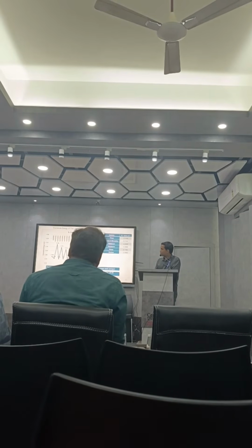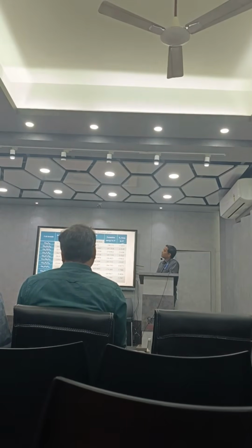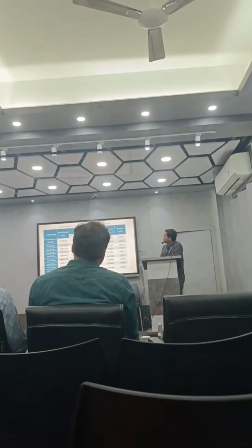So all gallium side doping has low formation energy. The atomic radius or ionic radius of the transition metal is nearly equal to that of gallium, so transition metal doped at the gallium side of gallium nitride is more preferable and more stable. Then we also studied 3 transition metal substitutions at the gallium side with vacancy. Here we found that substitution of iron at the gallium side with N vacancy has the lowest formation energy.